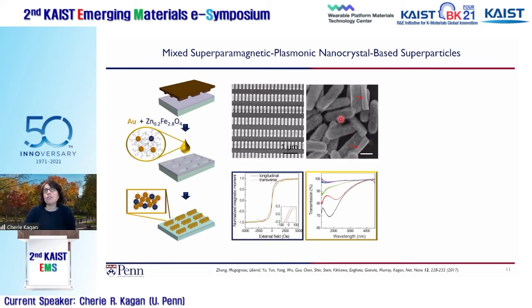These rods also still have an optical resonance. You can see it here, and it depends on how many magnetic particles we put into the system. As we add magnetic material, it reduces the amount of gold atoms that contribute electrons to the resonance, and it can ultimately block the path of the electrons sloshing back and forth across the rods. So we wanted to put in as many magnetic particles as we could to give them magnetic character, but not so much that we lose the resonance we would see optically. We ended up with a 3-to-1 ratio of gold to zinc ferrite.